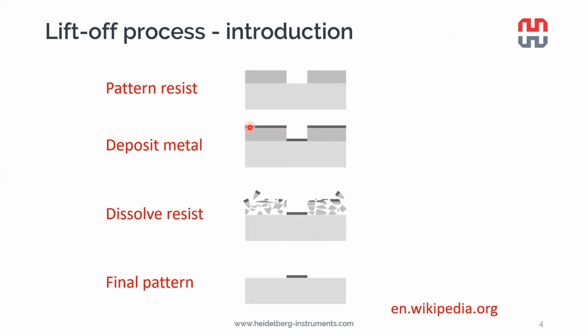And so that when you deposit the metal, most of the metal typically remains on top of the resist, and the parts you want to stay are deposited onto the substrate. Then when you put your sample into the solvent or chemical, then the resist together with the excess metal will be removed during the process, and you will be left with only the structures that you wish to remain, that were deposited in the hole in the resist. The key here is that you have an access point or several access points for the solvent to enter to the interface between the continuous metal film on top and at bottom to actually dissolve the resist.